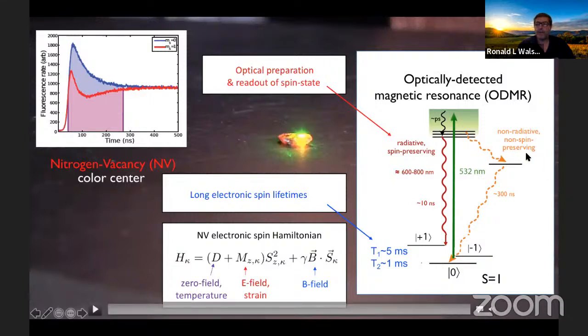Eventually, however, the ms equals 1 level would be pumped into ms equals 0 because of the decay process over a few hundred nanoseconds. And when that happens, what once was ms equals 1 is now ms equals 0, and you get returned to the same fluorescence rate for the two states. By the way, ms equals -1 would do the same thing as ms equals 1. This is just comparing the two.